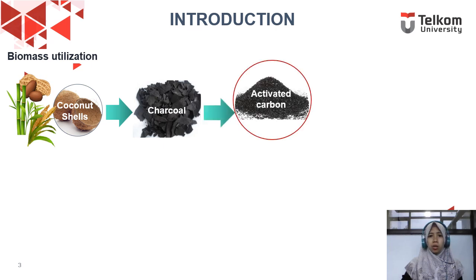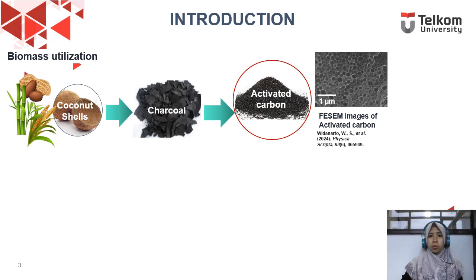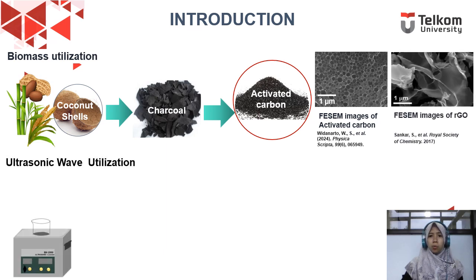Coconut shell, when carbonized, produces charcoal that is then activated, resulting in activated carbon with a higher carbon content compared to other biomass sources, as supported by the reference. However, the morphology of activated carbon, which consists primarily of pores, differs from the sheet-like structure of graphene. Therefore, additional processing steps are necessary to produce graphene-like material.